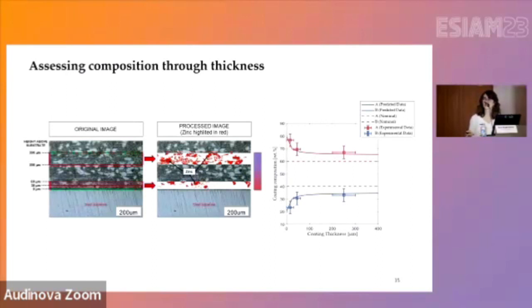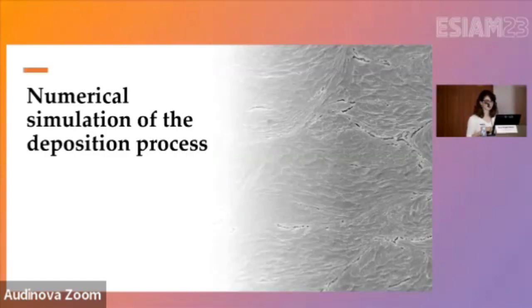In this case, for example, for a steel substrate, we have higher probability of aluminum to adhere to the substrate rather than zinc. So we have higher chemical composition of aluminum close to the substrate, and then it's changing as we are getting far from the substrate. At a distance of 300, 400 micrometers, we are getting to the stabilized chemical composition that can be captured very well with this predictive model.